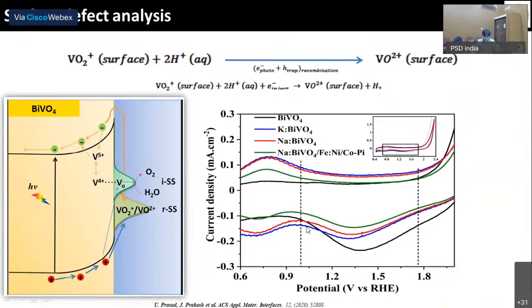But when we see the next part, the second region, there is a peak. This peak corresponds to the reaction of VO2+, which is available on the surface in the presence of our aqueous solution. It acts as a recombination site, and when the electron goes there, it gets trapped. So in the left hand side picture also I have shown the electrons, when they go to these recombination sites or trap sites, they get trapped, so they will not be further available for our water splitting reaction. So this is the surface defect analysis.